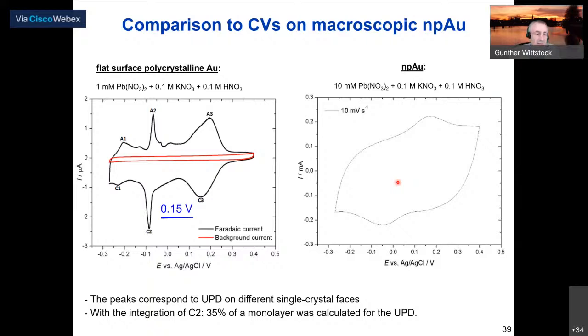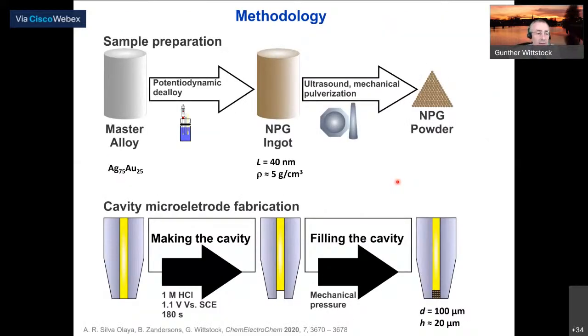So that was not really very encouraging. Then we went on and step by step learned the different tricks. And then I make a big jump, and now we are at the current state. This is the work done in Hamburg. We make a master alloy. We have this ingot. We de-alloy the ingot after very careful selection of the procedure. Then we receive that material. We mechanically destroy it and make a powder. And that powder is filled into a cavity microelectrode. It's now located at the end of such a cavity microelectrode.